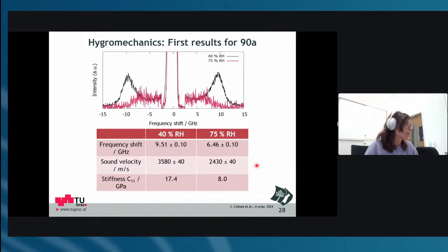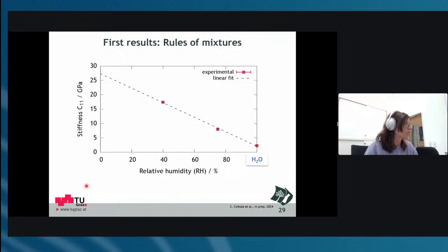And now what you can do, and this is only first results and a little bit of checking, you can take the peak, the stiffness at 40% humidity, the 75% humidity, and then you can also determine the peak width that you have in water and make use of mixtures. And then it's a similar trend as we've seen now.